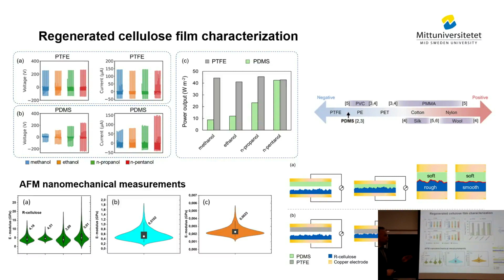So we saw that we have an effect, and it's not only related to surface structure, but it's also related to this change in crystalline structure. We did also some characterizations on how the elastic moduli look for the different materials. If we look at the cellulose, we have some changes. At least you have a wider distribution for the pentanol and also a bit higher value for the modulus. But it's not extremely big changes. But compared to PTFE and PDMS, it's a lot.